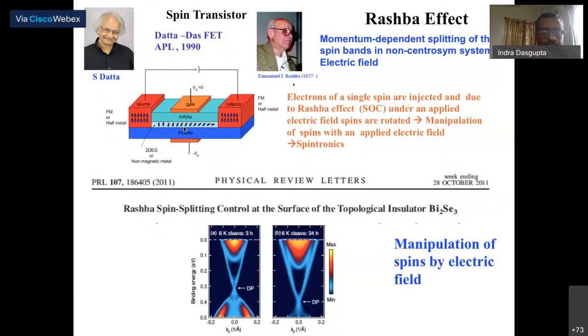Okay, so once you apply the electric field, we can tune the spins. And they will be delivered to the collector, provided they are aligned with the spin of the collector. Otherwise, they will not be delivered to the collector. And this gives rise to a transistor action upon application of an electric field instead of a magnetic field. This concept was devised in 1990, about 20 years ago, and still, of course, has to be realized, but the Rashba effect plays a very important role. People have also been looking at Rashba effects in topological insulators, again with the idea in mind that we can manipulate spins by application of an electric field.